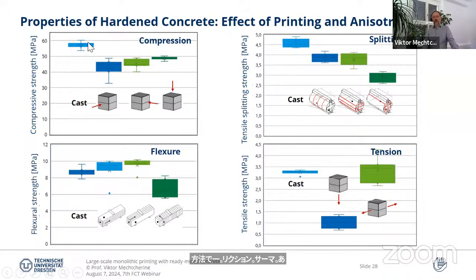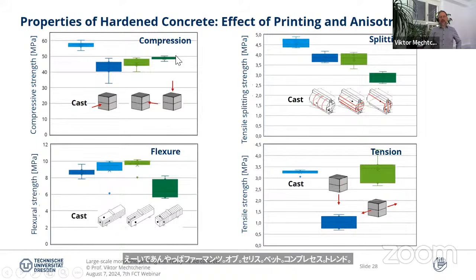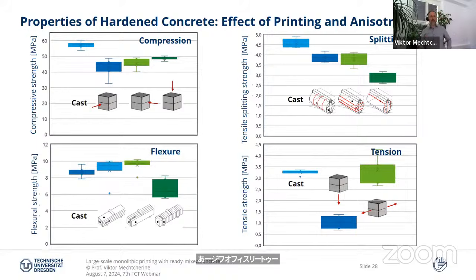And I compare for the same material, but cast in the mold. And you see that we have a little bit of difference in the performance with respect to compressive strength in this example. It mustn't always be the case, but here it is a little bit smaller, obviously due to compaction. In the print head, we do not have the same degree of compaction, but maybe there's also some minor effect of the joint. For flexure, we have for these two directions even slightly higher values, but in the direction of loading parallel to the joints, we have some decrease in the flexural strength, splitting more or less the same.